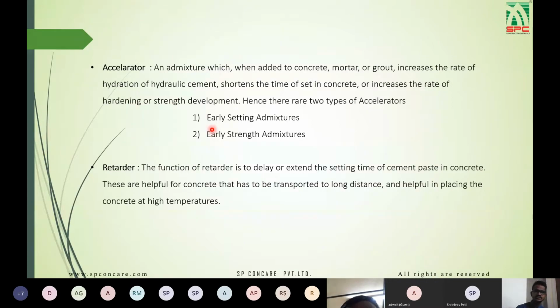So basically it has two types, early setting admixture and early strength admixture. The early setting admixture shortens the setting time of concrete, and it also increases the strength development. Whereas the early strength admixture just increases the strength development of concrete and does not affect the setting time of concrete.